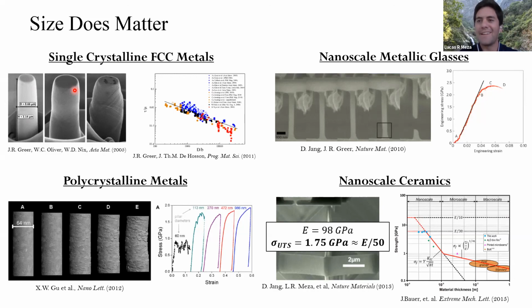Basically the atoms are free to move around on the surface, so you have lower strength. That doesn't really matter until you get to about 10-ish nanometers, which is also where you see size effects in stiffness - the stiffness doesn't really change at all until about 10 nanometers. That surface effect is really predominant in polycrystalline materials, where you see the free surface being detrimental. But here the free surface just serves to allow dislocations to escape - a dislocation starvation mechanism, as they call it.